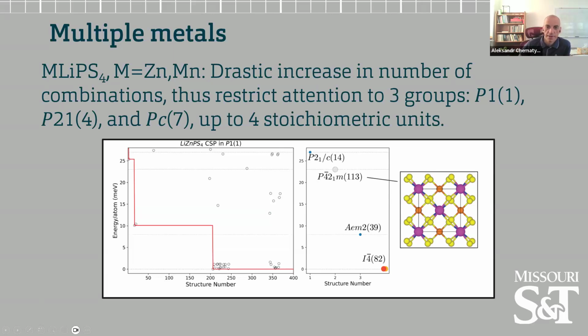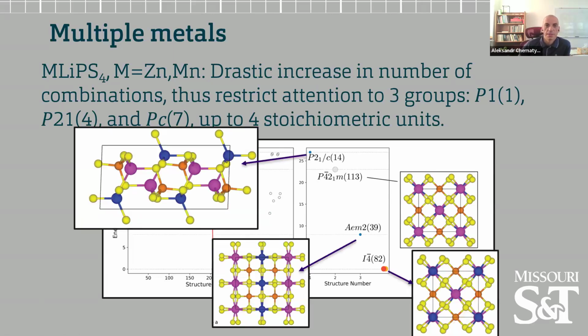And indeed, we find these different candidate phases. In this particular case, for zinc, there is also a known lowest energy structure. It is indeed in group I4-bar, group 82. And this is indeed also what we have found, in addition to some metastable phases. So again, it is a reasonable success in the sense that we were able to find the experimental structure here.